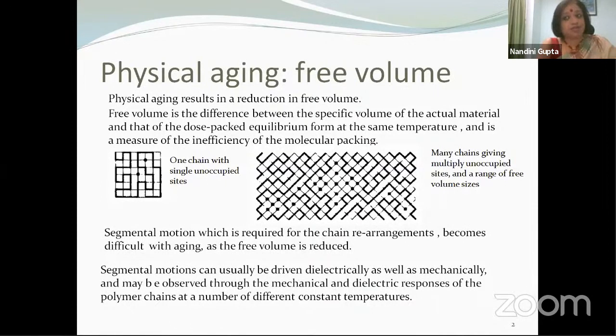It makes sense to talk about free volume in the context of dielectrics because many of the insulating materials that we use, for example, epoxy, which we use in the laboratory freely, do have an enormous amount of free volume. And what happens is that as time progresses, this free volume decreases. And the decrease in free volume has the same effect as you would expect.